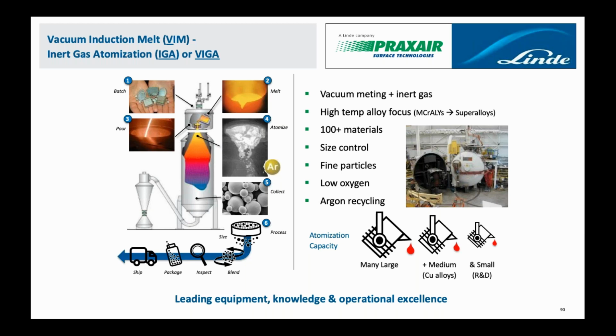So leveraging that experience we have making powders, on this slide, especially the metal alloys, we can make any or most of all the nickel and cobalt based superalloys, iron alloys as well. On Earth, traditionally we'll take refined materials, so elemental nickel, cobalt, stuff that's usually 99.9% pure, and we will put that into an induction melt furnace. We're going to do this at high temperature, and we don't want oxidation, so that furnace is inside a vacuum chamber. We will heat it under a vacuum, and then as it becomes molten, we'll backfill with argon. And once it's a liquid, we'll pour or atomize that. So the tundish will pour that melt. It'll go down a runner and feed a nozzle. You can see the melt in 2 and pouring it in 3 on the left there.